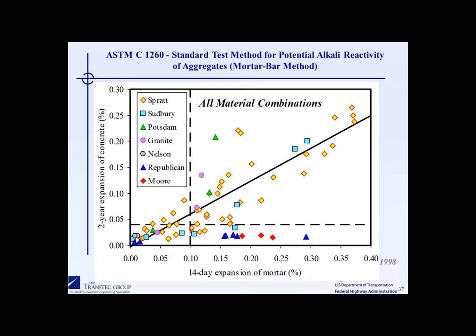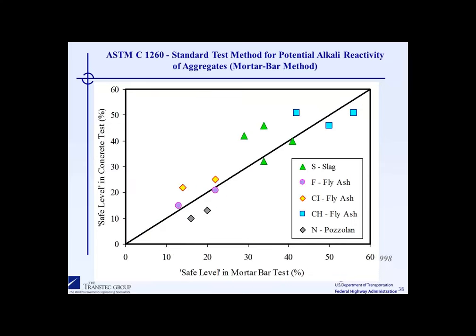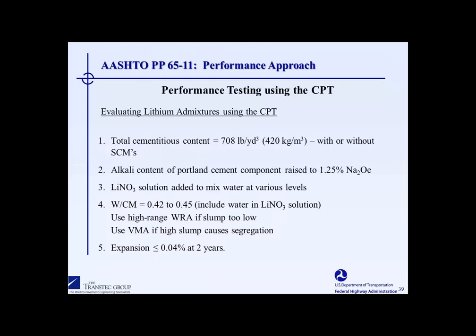Now, one question becomes, what kind of dosages of SCMs would you find that you needed if you ran the accelerated mortar bar test, and how does that compare to the concrete prism test? And that's shown here on this graph. This is showing the relative amount of SCMs that were needed in the mortar bar test on the x-axis versus the safe level that was needed in the concrete prism test. The black line here shows a line of equality. And what you see with this data set is there's a reasonable correlation in terms of the amount of fly ash, slag, or natural pozzolan that's needed to control the reaction between the two different test methods.